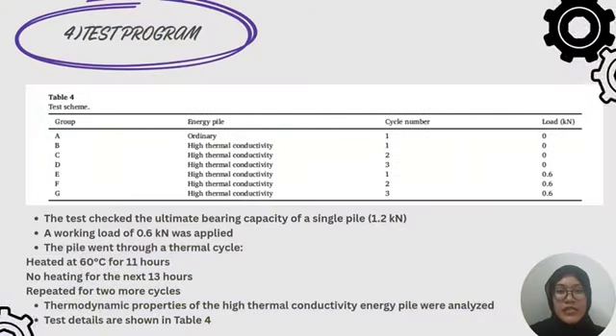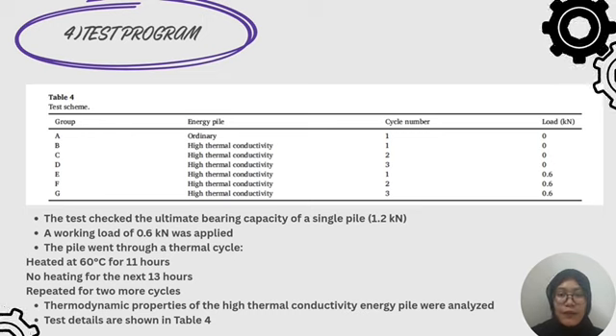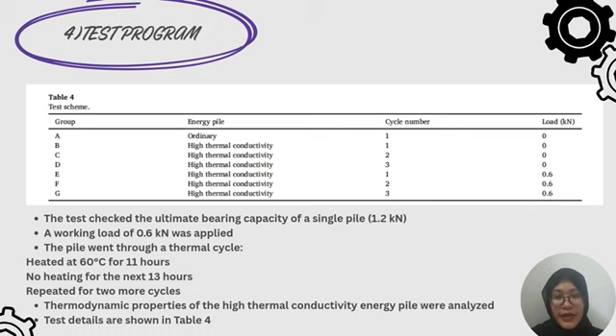In this test, we measured the ultimate bearing capacity of a single pile, which was 1.2 kN. A working load of 0.6 kN was applied. The pile was put through a thermal cycle. It was heated at 60 degrees Celsius for 11 hours, then left unheated for 13 hours. This process was repeated for 2 more cycles. Throughout the test, we analyzed the thermodynamic behavior of the high thermal conductivity energy pile. More detail about the test setup can be found in Table 4.